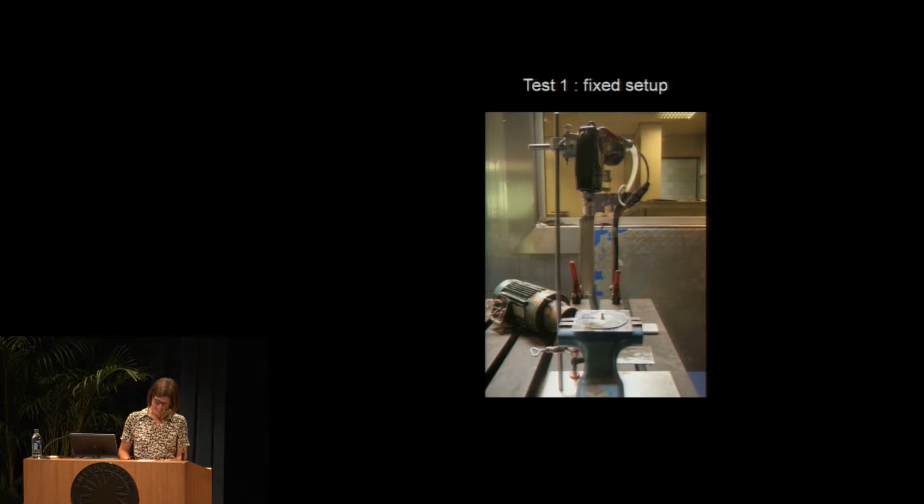I chose the parameters for this set also to be able to compare it to other blasting techniques, but I should say that it's almost impossible to compare because so many other factors come into play, such as hose length, the age of your dry ice, your particle size, which could vary, the humidity, etc.